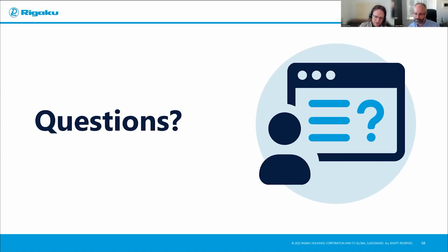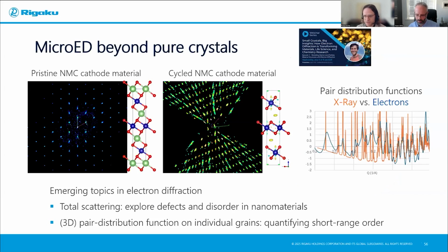Well, this is, let's say, just a rough guideline. What this basically says is it is still a crystallographic technique, and except for these cutting edge applications like pair distribution function and total scattering, you just need your samples to be crystalline in the first place, and you need to have diffraction to at least, let's say, 1.2, 1.3 angstrom to have a chance with a structure solution from single crystal analysis methods.